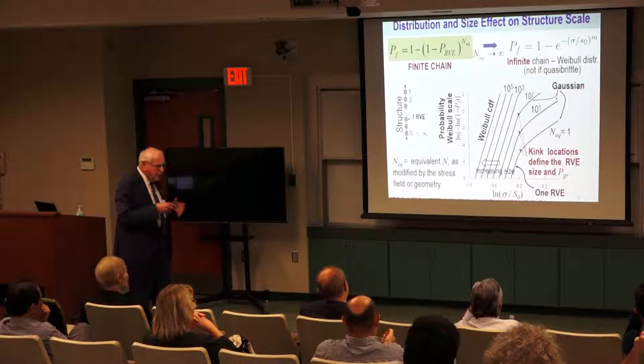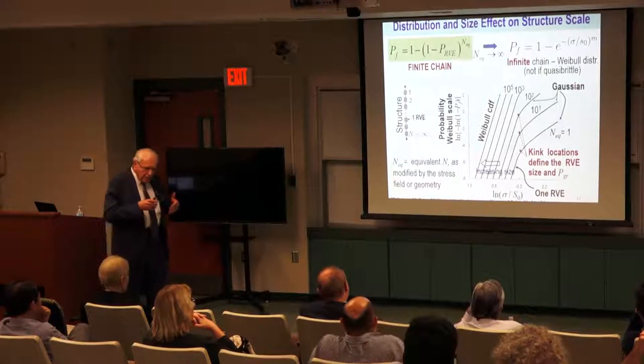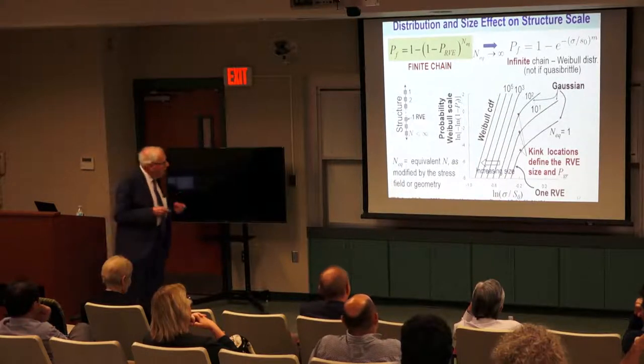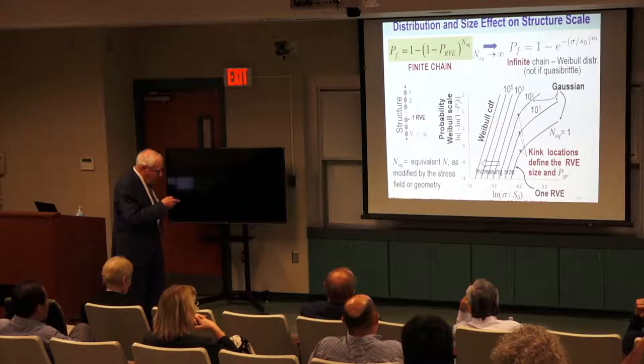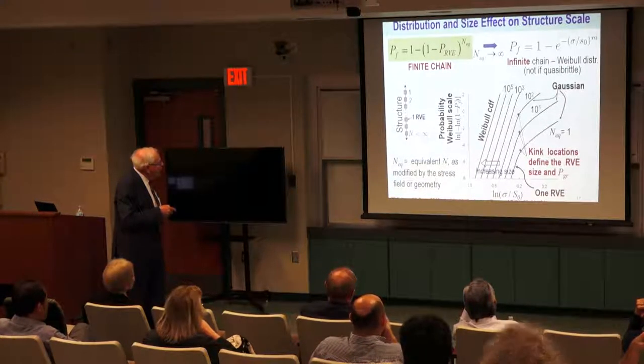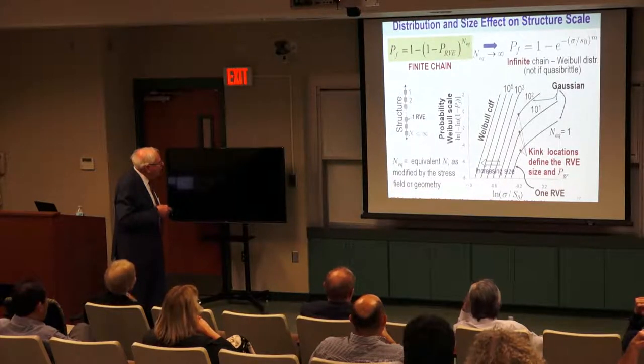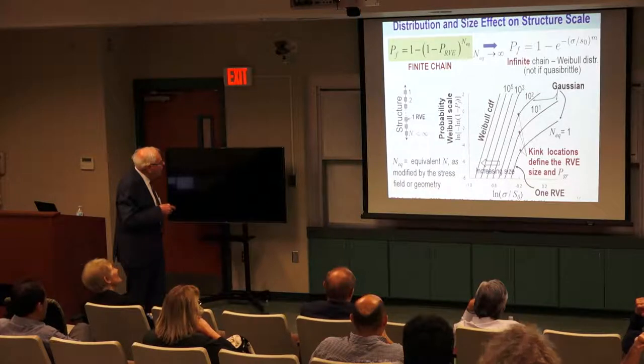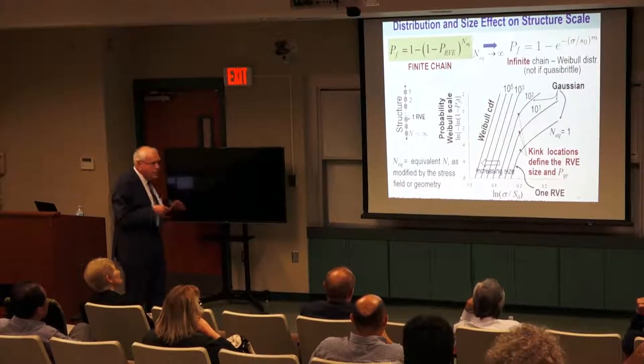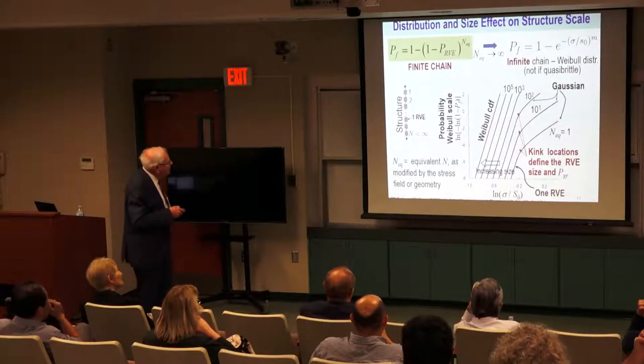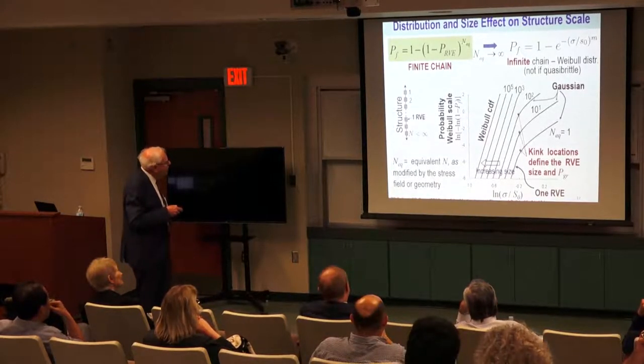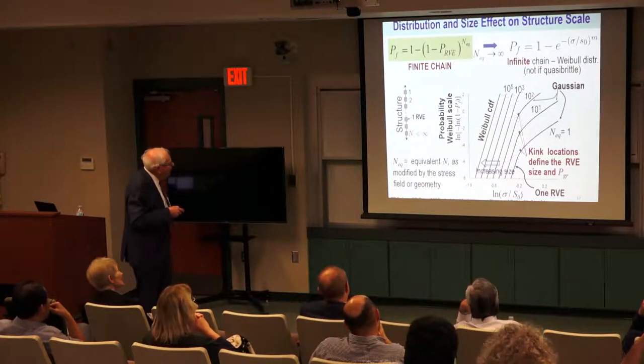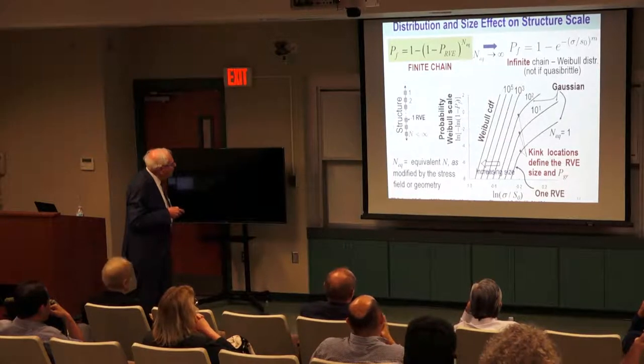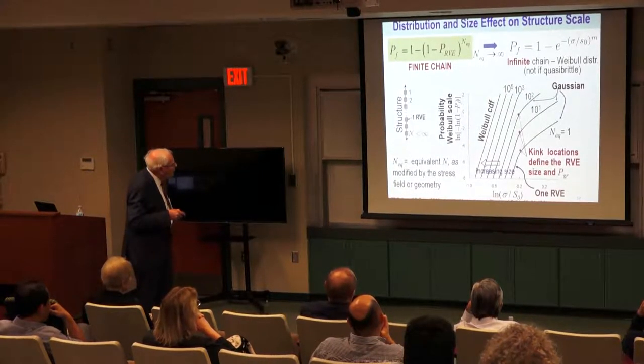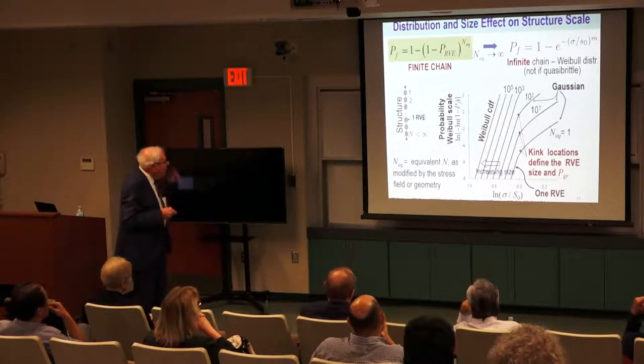And when we consider structures which have so-called positive geometry, failing as soon as one element fails, though not every structure does it, reinforced concrete does not, then we need to calculate the failure probability of the structure as a whole. So we consider a chain, and basically what we are doing, 1 minus failure probability is survival probability. And that structure survives if all the representative volume elements survive, the joint probability. These are identical, there is an exponent n, the number, but it must be scaled by stress, I will not talk about this, it's the probability of 1 RVE. Now if you take this to infinity, and if you know that this probability is a power law, you get this Weibull distribution. But for quasibrittle structures, you cannot do that. You must work with this.